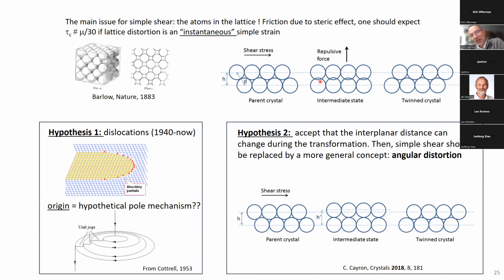So that's why people came to say, okay, we will solve the problem by assuming that we have dislocations to go from here to here. And not only do we have dislocations, but they assume that the dislocation creates the martensite or creates the twins. And to me, it's a problem because in that case, you have to explain where the dislocation comes from. If they create the twins, explain to me where they come from and how they can be stacked regularly on planes with very specific Burgers vectors. So people try to cope with that by imagining a pole mechanism in which at the beginning we have only one dislocation that turns around one line, but this spiraling dislocation has never been observed by TEM.